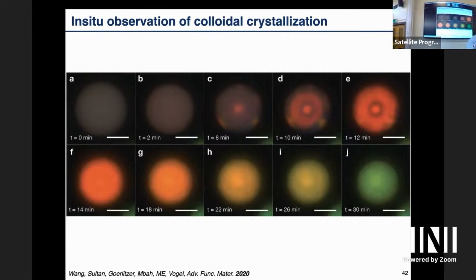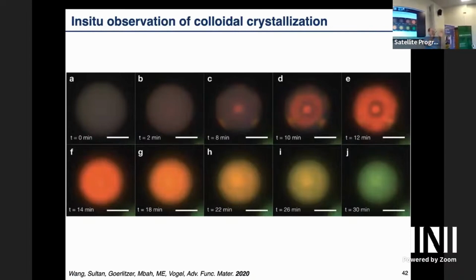And maybe just as a very quick summary of what we know about how this forms, without really proving it to you here. You start with a ball of more or less disordered colloids inside. Then the droplet shrinks, so the colloids get squished together. They start forming order in layers, so there's layering on the surface. It's a little bit like a smectic liquid crystal: there's layering, but no order within the layers. That's when we see this dot here, and this dot gets brighter.